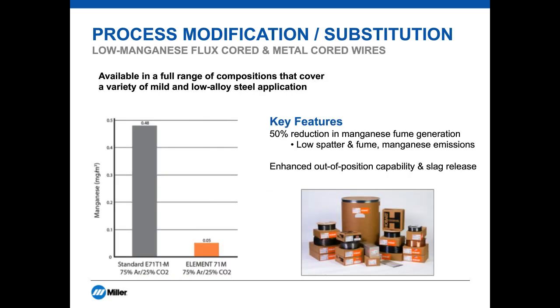Another option is to choose a filler metal that targets specific components of the fume. This graphic gives a comparison of manganese exposure using a low manganese flux cord wire as compared with a traditional flux cord wire. Reductions in manganese exposures of 50% or more are possible with these low manganese filler wires. You should note that this testing was done in our test lab under controlled conditions. You should always do exposure testing in your own facility to verify the results due to the large number of variables that affect fume exposures.